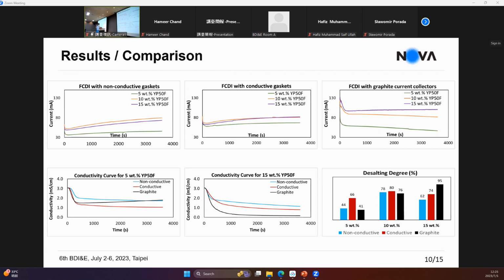And also, it was mentioned in the previous presentation, when you increase the carbon content in the flow electrodes, the viscosity dramatically increases. So with 15% or 20%, and we saw it by CFD simulation, there is no chance of having a mixing of a flow electrode. It's fully laminar flow. But with 5 and 10%, you can create some mixing of the flow electrode. And we believe that this rugosity on the surface of a 3D printed gasket adds that mixing. And therefore, it promotes for the conductive gaskets the accumulated benefit of being conductive spacers and promoting mixing. It gives better performance than the graphite current collectors.